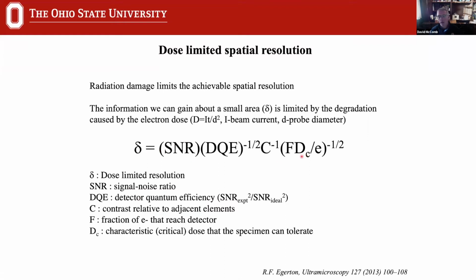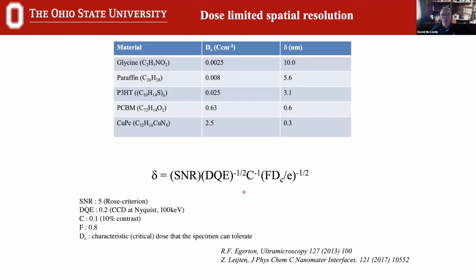It depends on the critical dose to damage of the material, that's just a property of the material. It depends, for example, on the signal to noise that we actually want to achieve in our data, the detector quantum efficiency of our device, and a number of other factors. So this is going to limit what we can actually achieve. And here we look at, from the literature published in JPhys Chem C, some dose-limited or critical dose to damage in a number of organic systems, and the calculated dose-limited resolution.